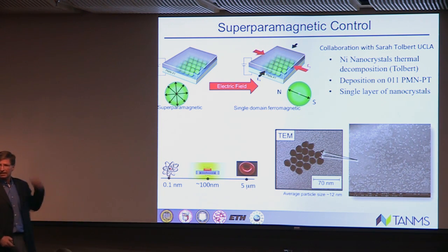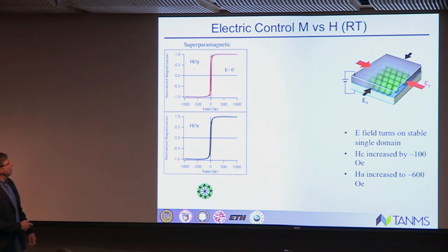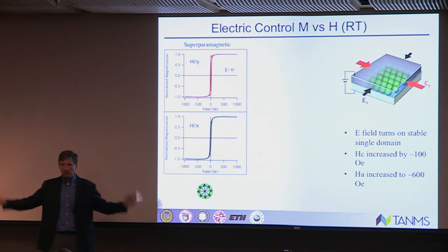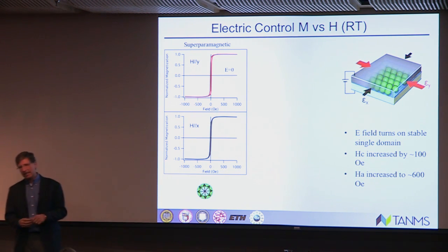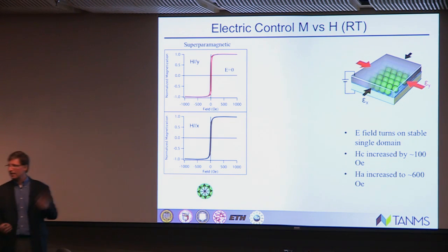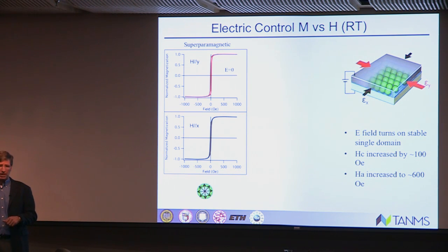Well, now let's look at some data. So this is the sample without an electric field. And we measured the magnetic states along two directions. One is the X and one is the Y. So here's the X and here's the Y. Notice they look almost identical. Very little hysteresis, so the argument is that it is superparamagnetic at room temperature.